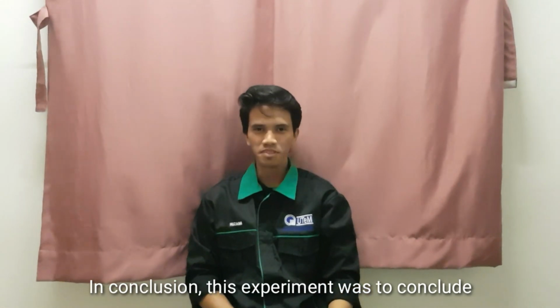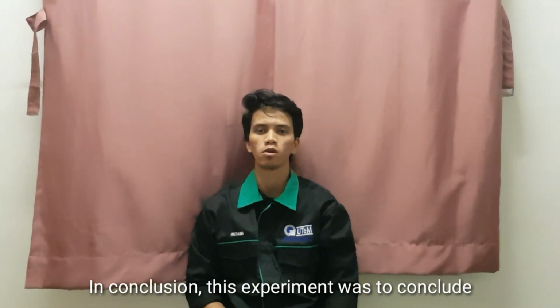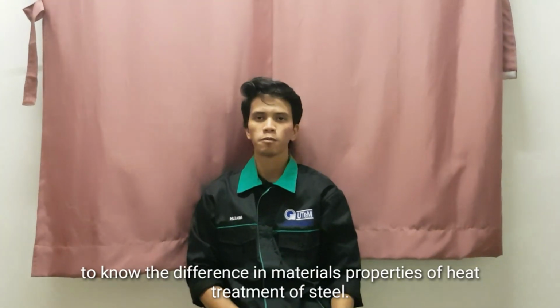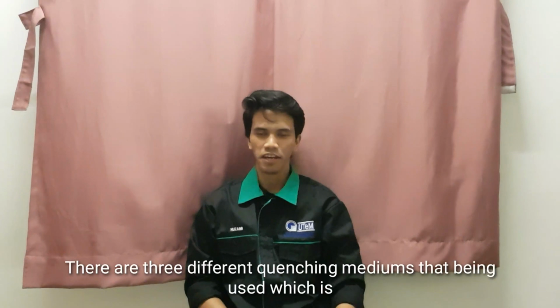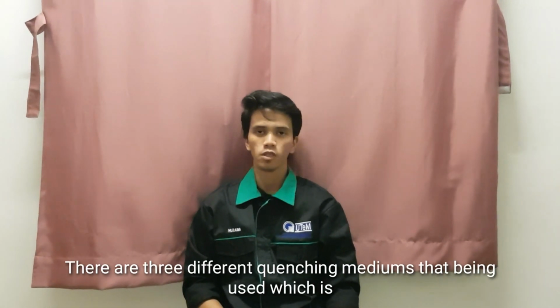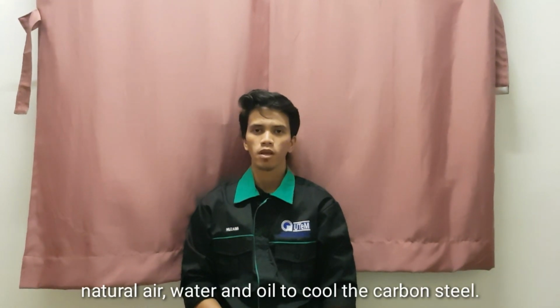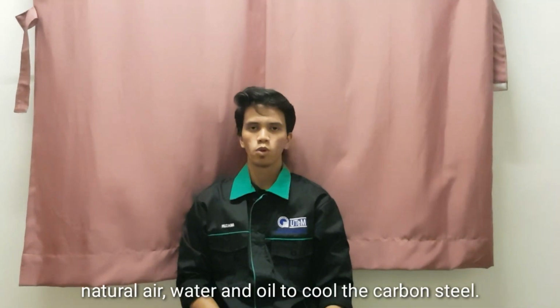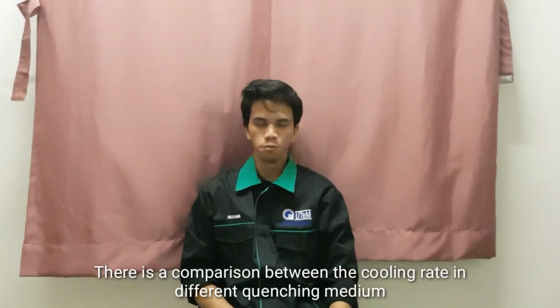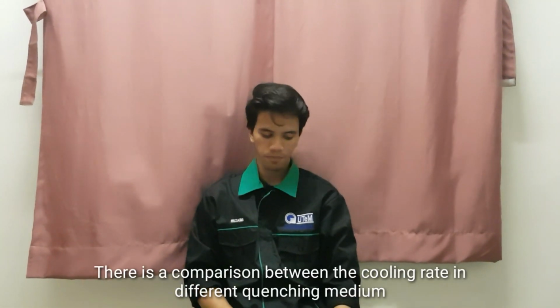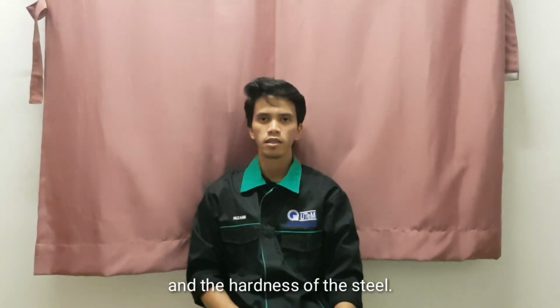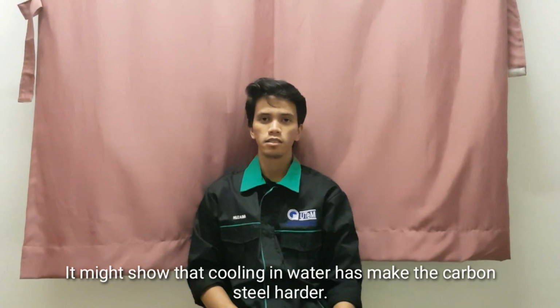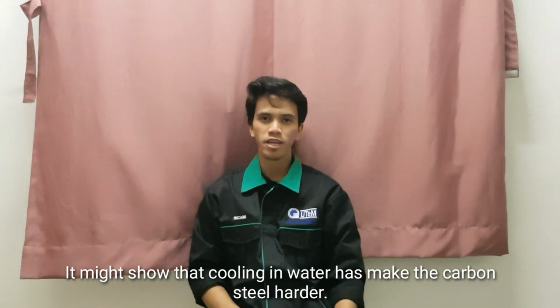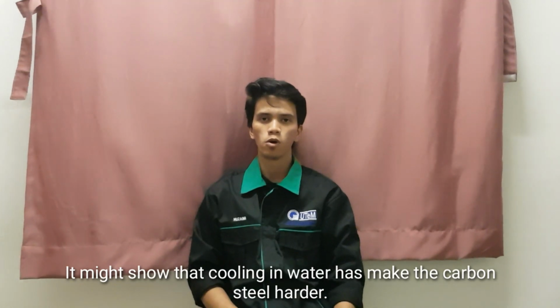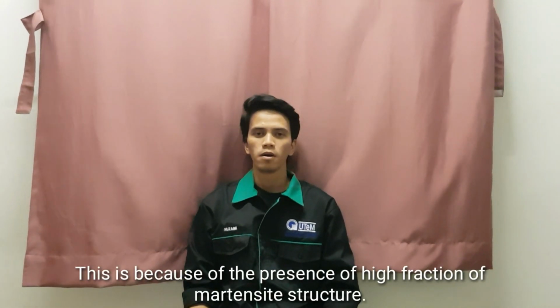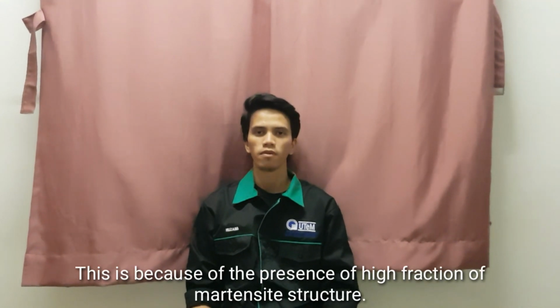In conclusion, this experiment was to know the different material properties of carbon steel. There are three different quenching mediums that had been used, which are natural air, water and oil, to cool the carbon steel. There is a comparison between the cooling rate in different quenching medium and the hardness test of the steel. It might show that cooling in water makes the carbon steel become harder. This is because of the presence of a high fraction of martensite structure.